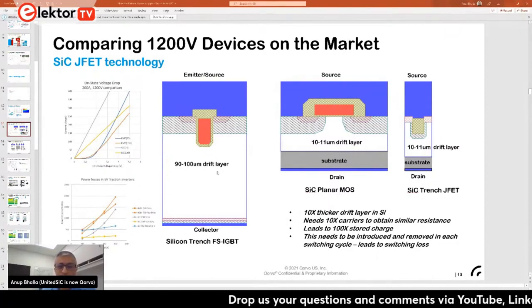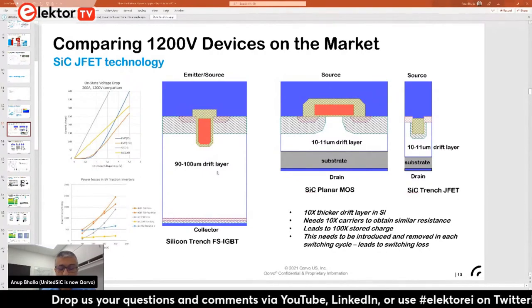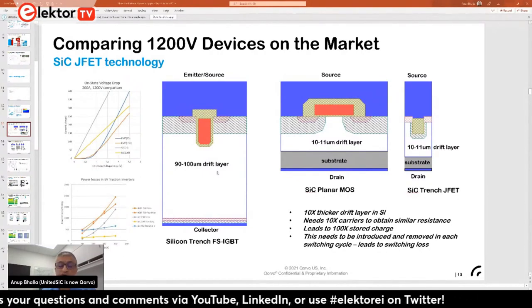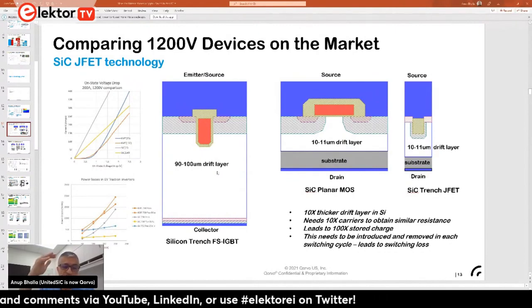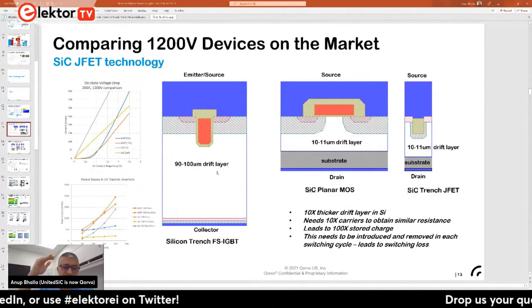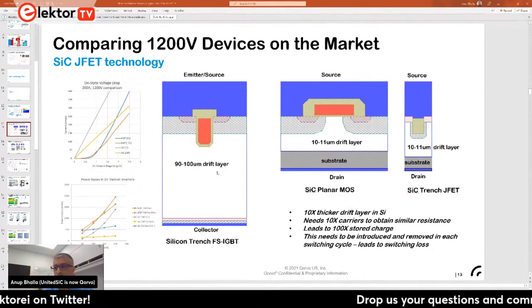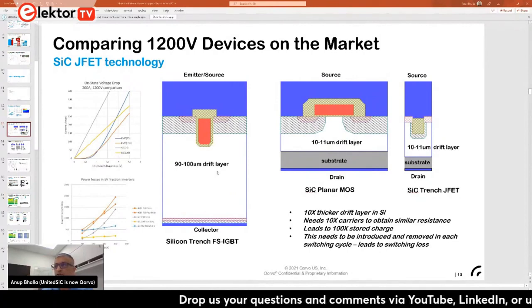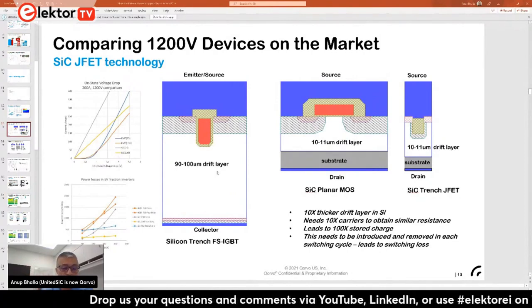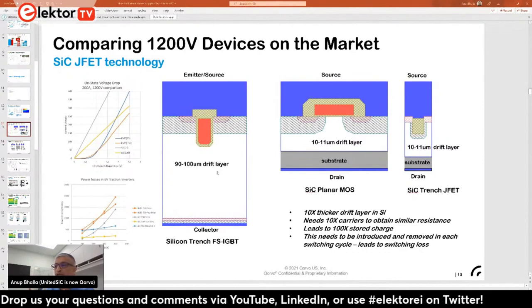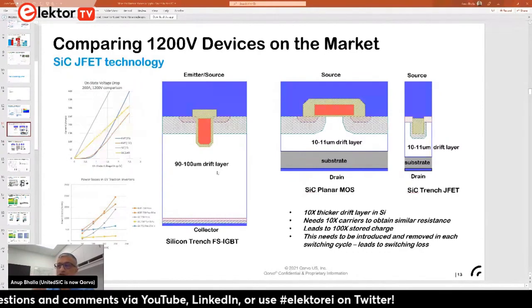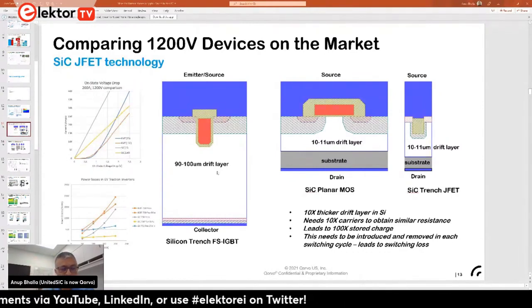This just comes from the fact that in silicon, because the critical field for breakdown is so low, you have to use a much thicker voltage supporting region, and you have to dope it lightly, which means its resistance tends to be high. And to cut that resistance, the technique is, you inject electrons and holes into that region so that it'll have a low resistance. But then once you do that, in every switching cycle, you've got to move the charges in and out, right? Which ends up slowing down the IGBTs.